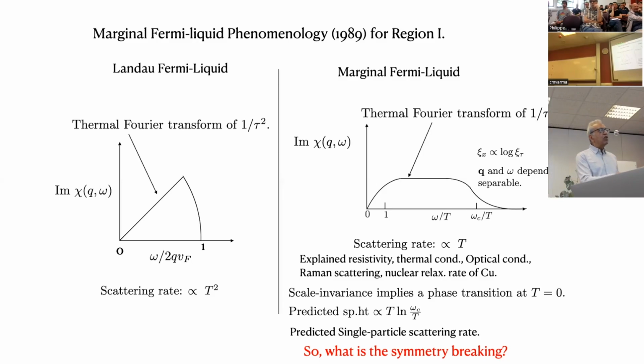This has to be an odd function again, as I mentioned. So you see, all that we are doing as we go to lower temperature is to pile up the weight at lower and lower energy, and in the limit of T going to 0, there is a discontinuity. Therefore, the Kramers-Kronig gives us a log. A log of T means that there is some criticality in the limit of T going to 0. Okay?